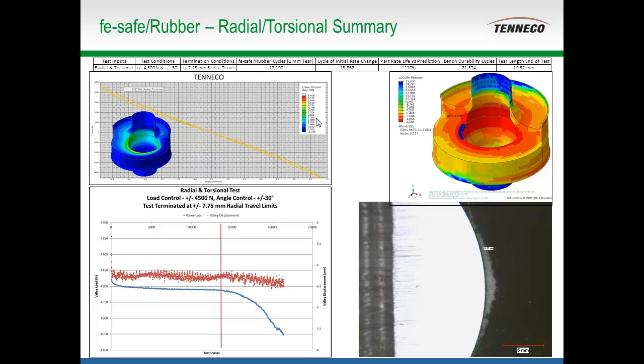From an analysis standpoint, we did not analyze if there would be self-generated heat, but we had infrared thermocouples monitoring the part. The parts never rose above 30 Celsius. Our lab is pretty much maintained at 22. So there was a few degrees Celsius temperature rise, which obviously with any dissipative material, you'd have to test it unacceptably slow to get no temperature rise. The material properties between 22 and 30 Celsius, especially with natural rubber from a fatigue standpoint, I guess we ignored those effects. Maybe the correlation would have been slightly better if we would have, but yeah. We made sure we didn't have a temperature rise issue.